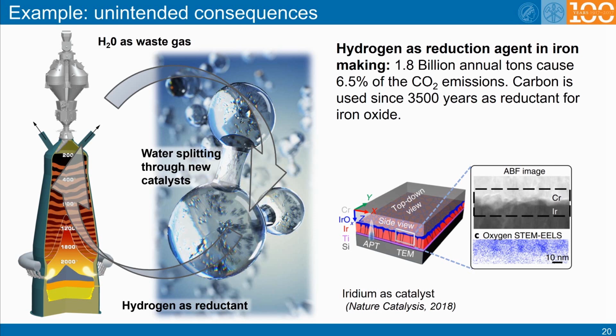For about 3,500 years, iron ores have been reduced by using carbon carriers as reductants. This leads to a substantial production of CO2. As a rule of thumb, currently about 2.1 tons of CO2 are produced per 1 ton of steel. When considering the huge amount of steel globally produced, it becomes clear why about 6.5% of all CO2 emissions on the planet come from the steel industry. Therefore, the approach of using hydrogen as an alternative reduction gas is a very sensible approach, as the resulting emission would be just plain water.